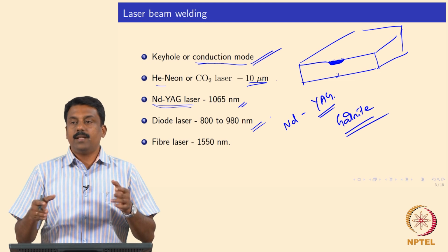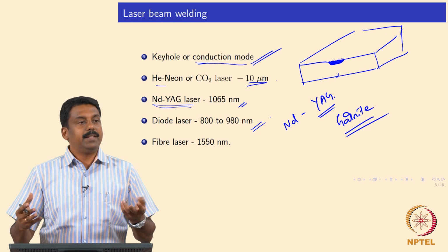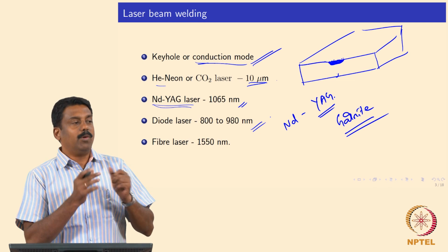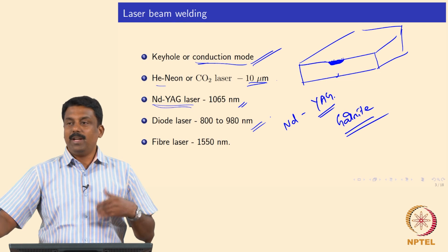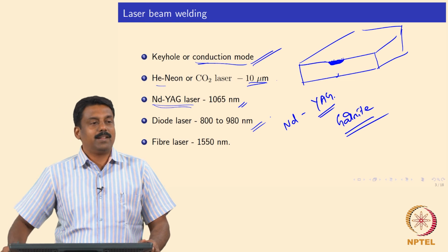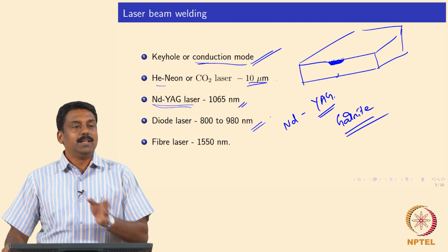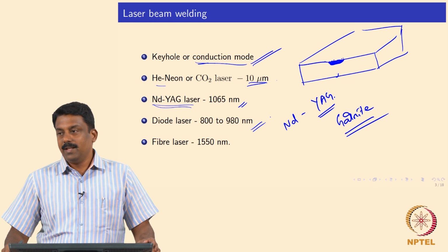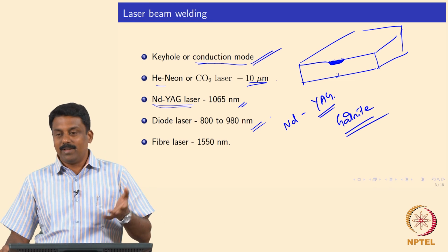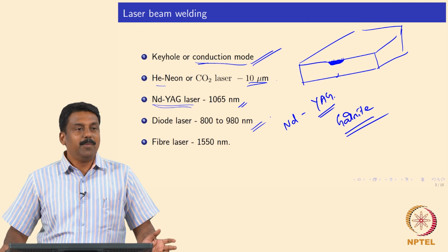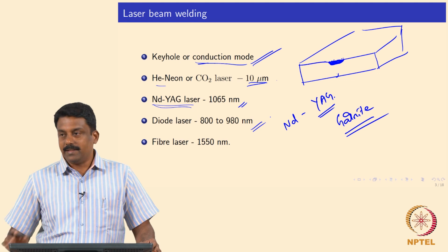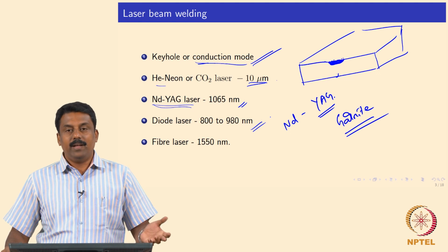Okay. So the solid state laser rod, you will have to replace after 5 years or so. Initially it may generate 4 kilowatts, but after 5 years you would never reach 4 kilowatts because of the erosion of the Nd-YAG crystals. So we will end up losing output power. After 5 years, getting 2 kilowatts from a 4 kilowatt system is itself very challenging. The same goes for diodes as well. Diodes also degrade over time in the excitation cycles, so we will have to change the diodes.